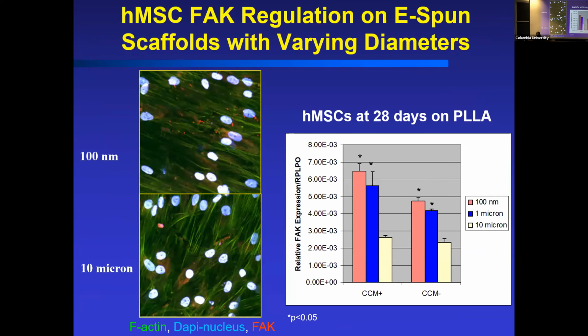So we've shown in a number of studies that it does affect cell adhesion. And so again, if you get down to that small, micron scale, you can really enhance cell adhesion as shown here. This is just some of the actin filaments, as well as we looked at focal adhesion kinase expression as an indicator of integrin adhesion. We see that's expressed really high, and you get really organized integrin filaments.